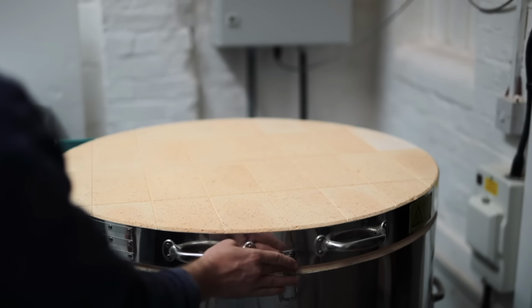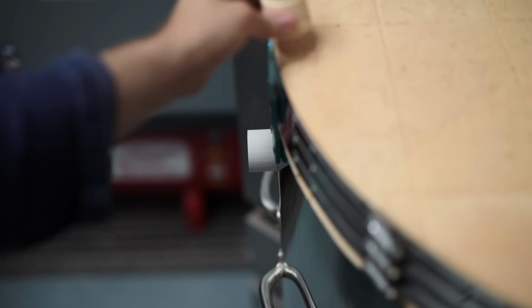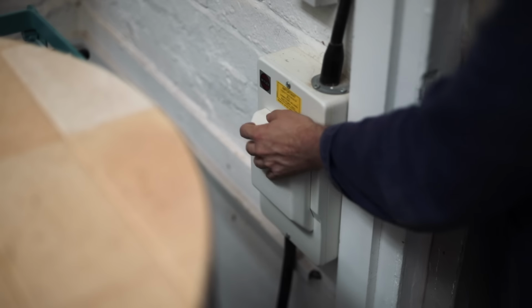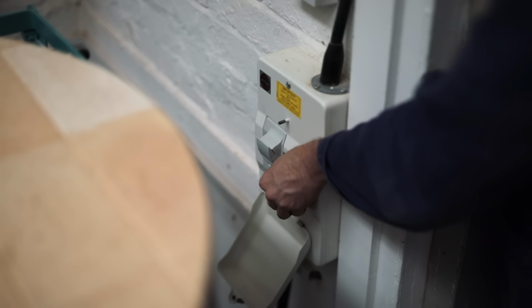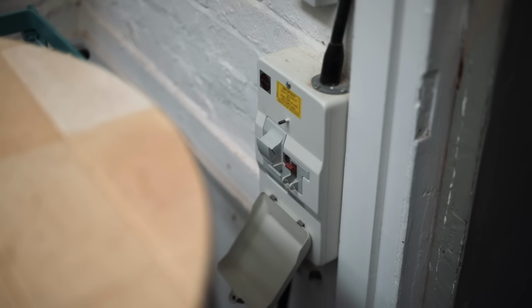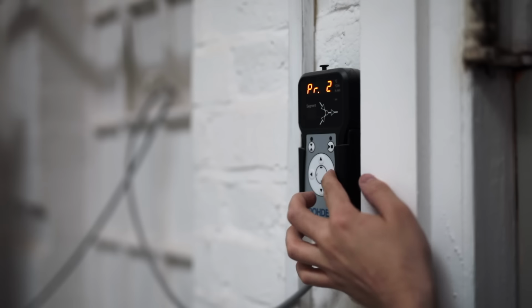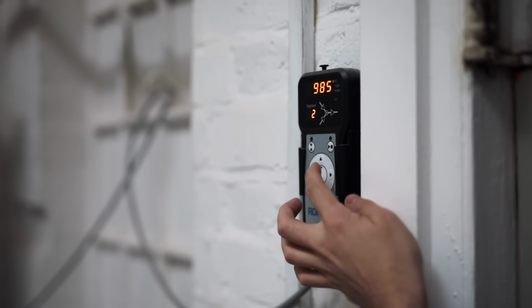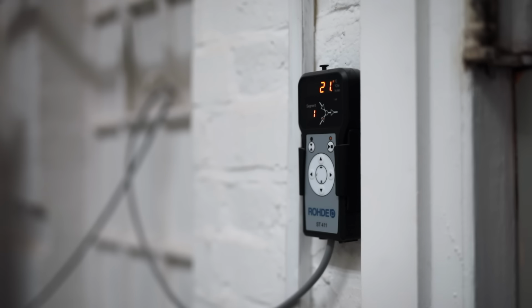Once full, the kiln is sealed up, and I remove the bung in this spy hole so any excess moisture and gas can escape. The power can then be switched on, the program set, the firing initiated.